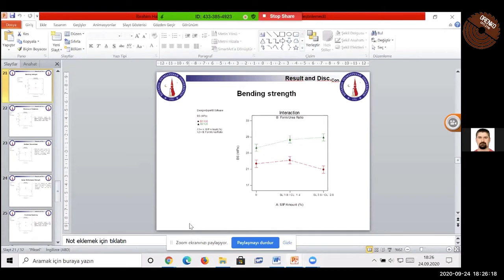It was thought that it helped to improve bending strength properties. However, the 1 mol resin group, which has the highest amount of the MIP waste, shows the lowest bending strength properties. In this group, with MIP waste loading, bending strength values declined. All manufactured groups satisfied standard requirements for bending strength. It's about 13 megapascals.